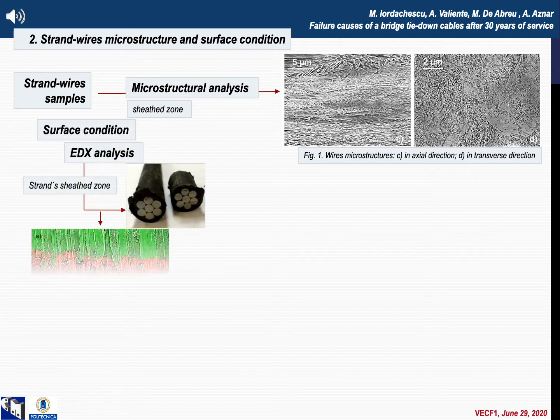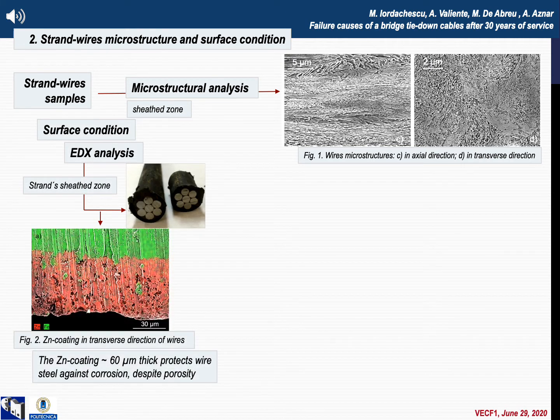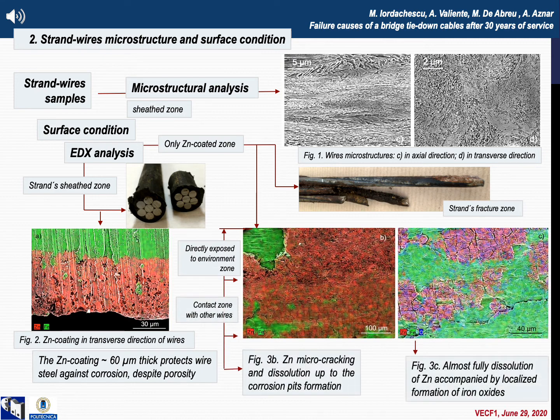The surface analysis of the wires in areas protected by the polyethylene sheet shows that they still preserve the zinc coating generated by galvanizing as consumable barrier against pitting corrosion. According to Figure 2, which presents the results of the EDX analysis acquired on a wire sample cut in transverse direction, the zinc layer of about 60 microns thick and despite its porosity continues to protect the steel in the sheeted strands. The situation changes drastically in the unprotected areas in the proximity of strands failure.